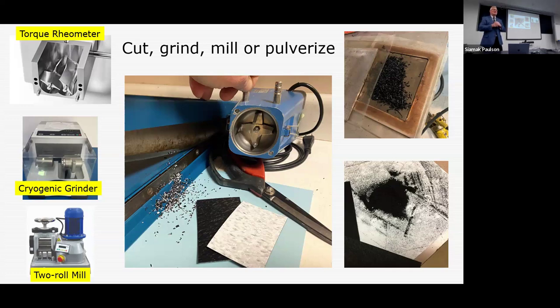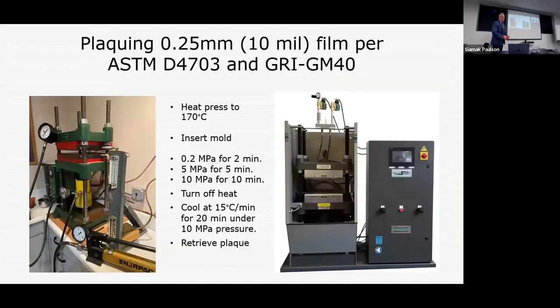Oh, I see some long faces. Maybe people don't believe. You must be very good at this. You need to make that plaque very well and have a very keen interest in this. You can crush this material. Please realize that a lot of these materials are made on either blown film or cast lines, and they're multi-layers. So now you'll grind this by one of three methods: torque rheometer, cryogenic grinder, or two-roll mill. You'll take this and form a powder and then create a plaque.